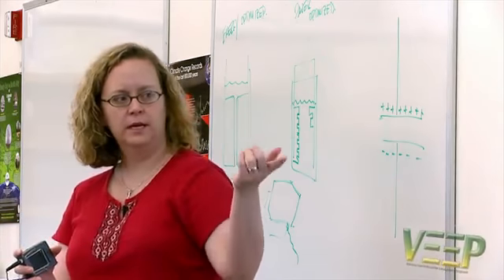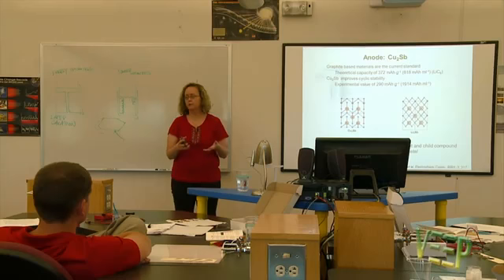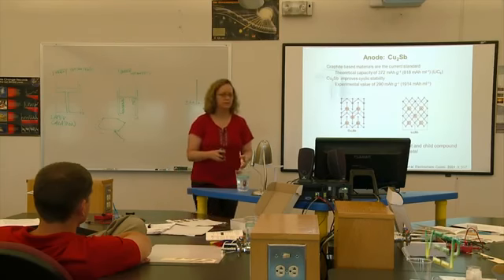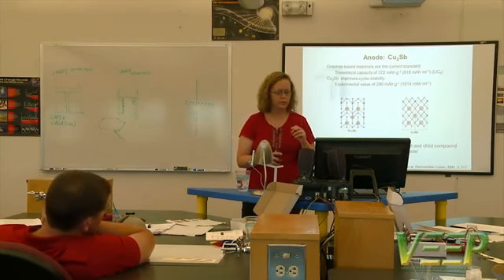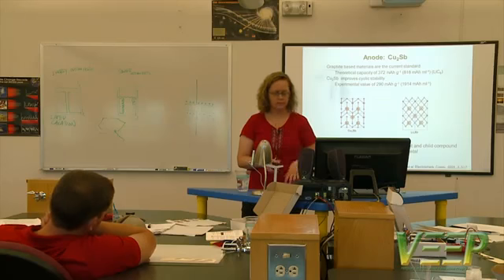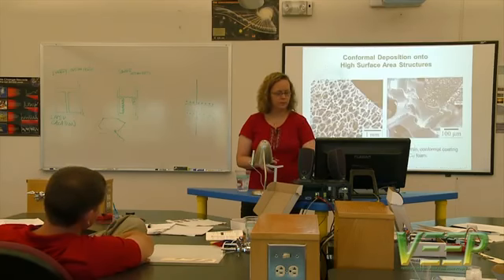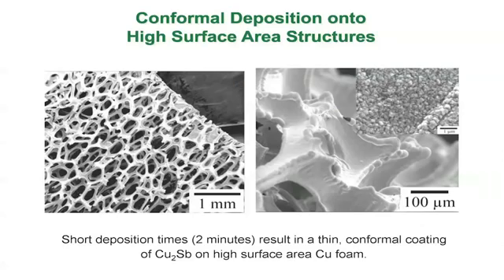So we picked an anode that chemically can't plate lithium metal so that we could make it safer. The other good part about this material is that it is really conductive, so it dissipates heat really well. This is what it looks like when we coat it on our foam. So this is what the copper foam looks like.